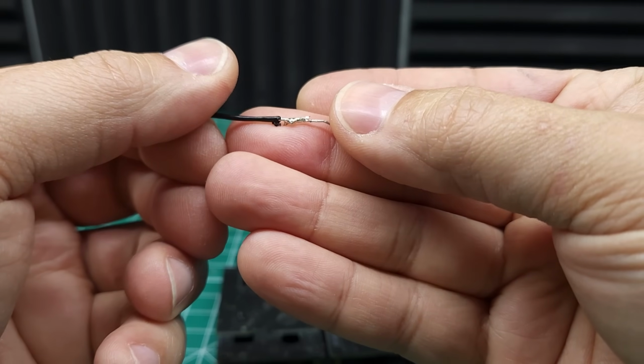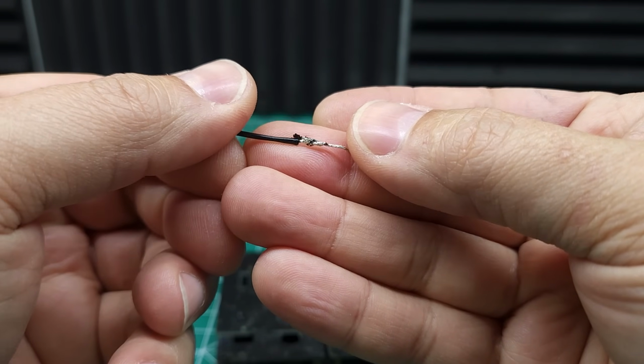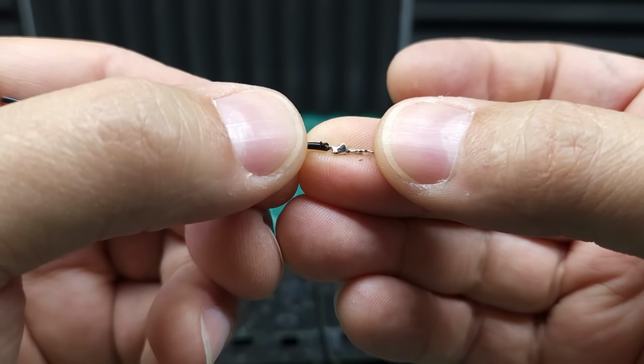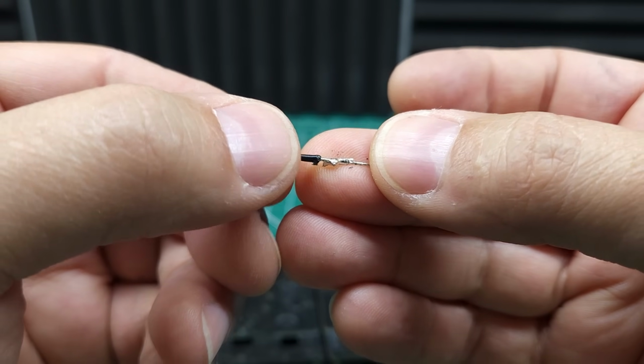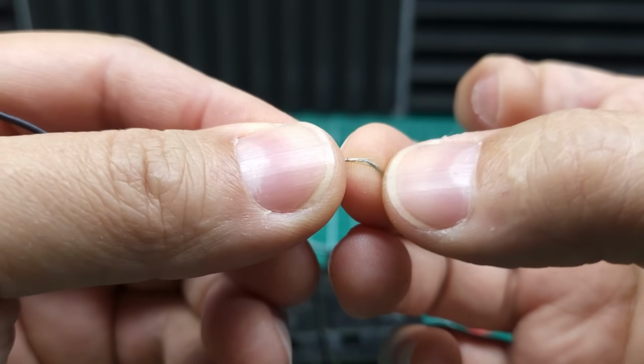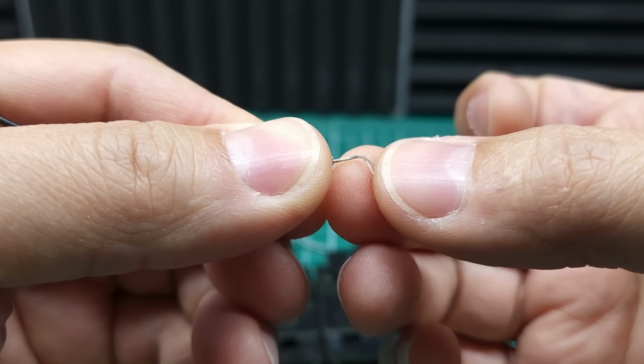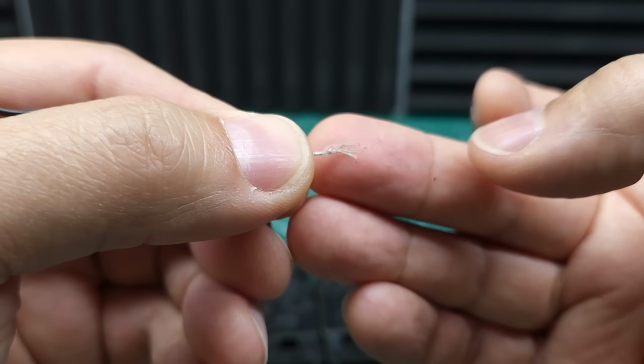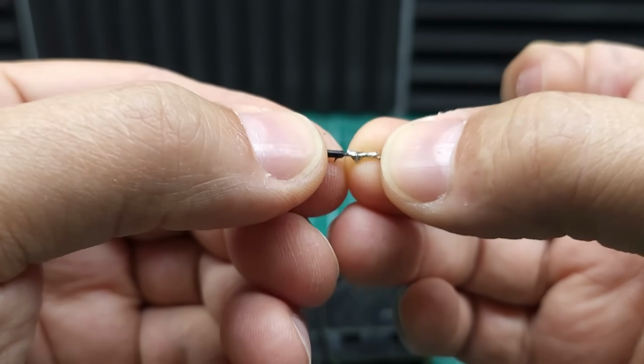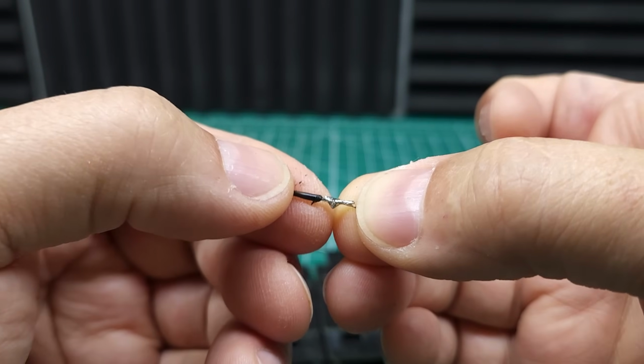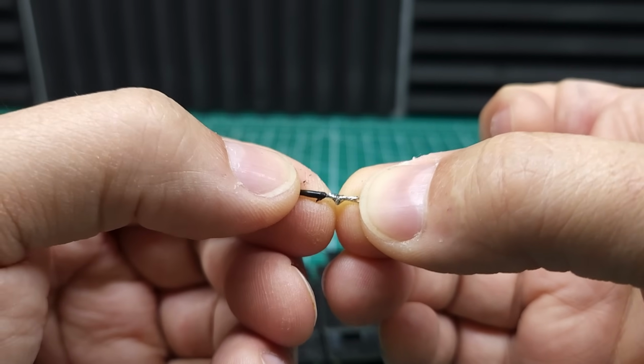So as you can see, first the insulation came off, then the wire strands themselves broke apart. And that kind of makes sense because whereas the solder itself isn't as strong as the parent material, often when you get a failure of wire, it's going to be strands that break individually, not everything breaking at once. And each one of these individual strands isn't as strong as this joint is. That being said, you definitely don't want to use a solder joint in a mechanical application.